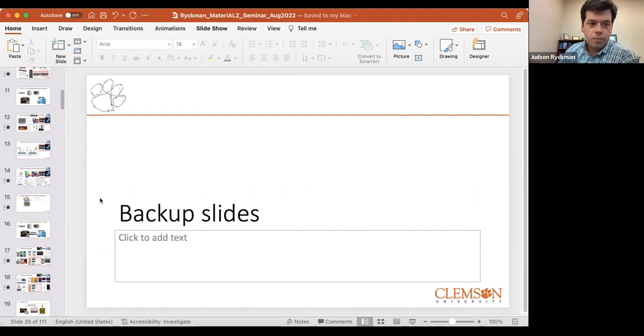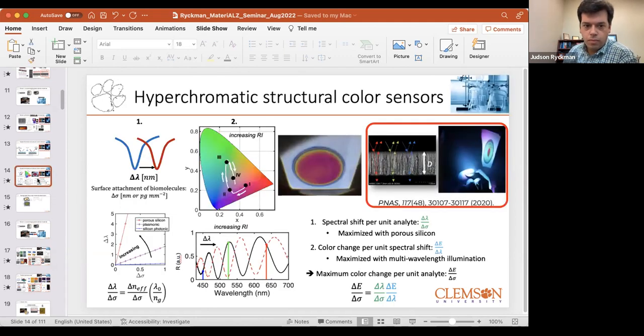So going back, my question about the wavelength, and you were saying that you were working on the infrared, but I think for the sensing, you were working with visible, is that right? So with silicon, even with polysilicon, when you go to visible light, do you not just get attenuation of the photonic modes because of absorption above the band gap? How does that work? I guess we really benefit from the fact that it's porous. So our silicon fraction goes way down, and then it's oxidized. So that further reduces it. I see. So it's really mostly silicon oxide with the wide band gap, and then the effective medium theory.